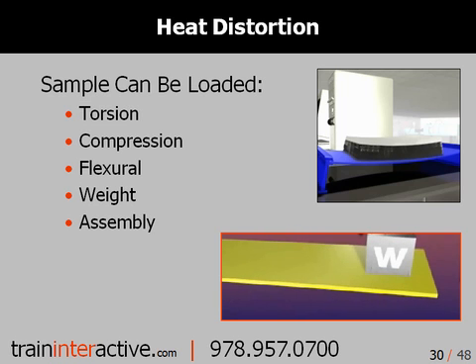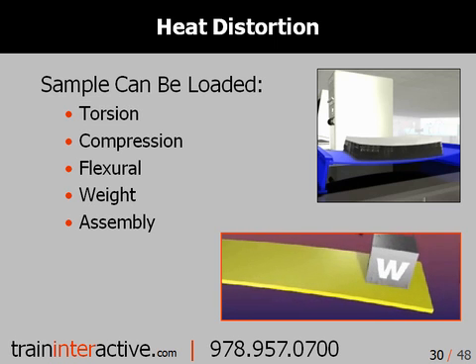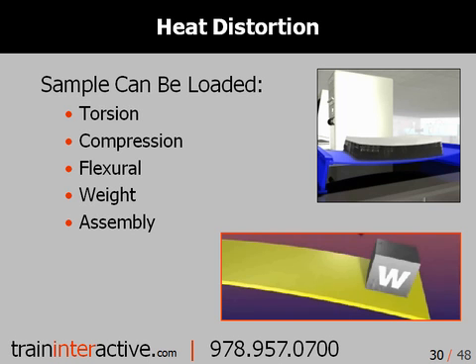Ultimately, what we are suggesting is that you test your part in a manner realistic to its application under heated conditions. This will give you a great relative measure of how the part will perform in the field. For example, let's suppose you mold a paper tray typically found in an office environment. The product will often be placed next to heat-generating office equipment, such as a copy machine, computer, or a computer monitor. You can simulate a loading of flexible paper through the use of a silicone sheet cut to the size of 8½ by 11, the standard paper size in North America. When heated, you can measure the deflection of the sample after a period of time, or measure the time required for the sample to reach a certain amount of deflection.